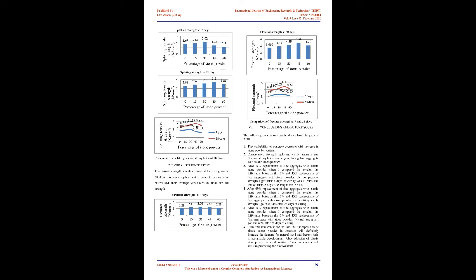The flexural strength was checked at the age of 7 and 28 days. 3 beam specimens were cast for each replacement, with a total of 30 beam specimens cast. The flexural test has been done by Universal Testing Machine.